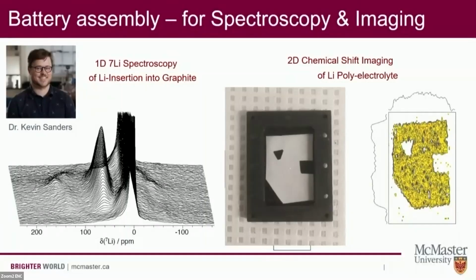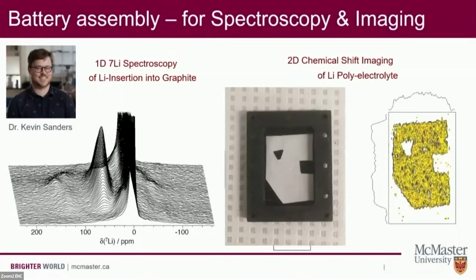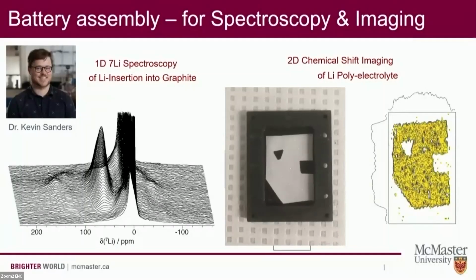It might. In the iron case, we haven't done those studies, but for silicon anodes, for example, we've gone to 200 cycles to try and look at phase changes at long cycling. There you give up the paramagnetic interaction, so it's a bit of a different question, but certainly we're aiming to get to longer cycle lives. You've got so many different lithium chemical shifts and shieldings, and then with the calculation possibility, maybe you've got a hint. That's exciting. Yeah. First time maybe that we could see that.